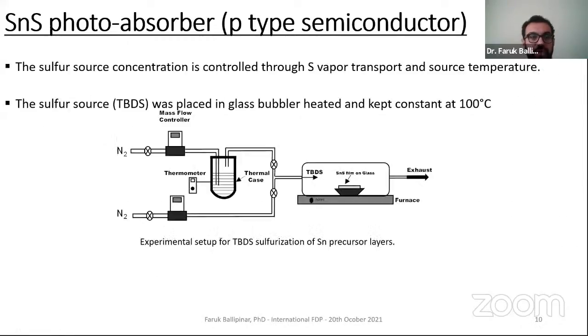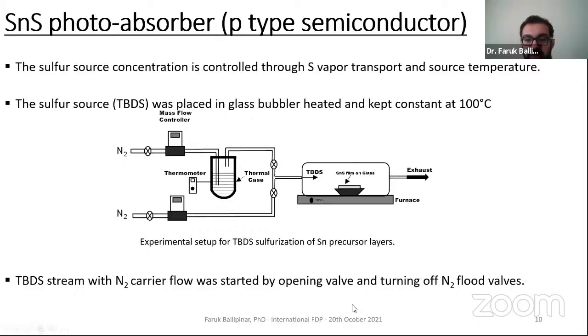Okay, so this is the experimental setup. We put the substrate in the middle of the furnace, and the TBDS source was placed in this glass bubbler and heated, kept at 100° below the boiling point of this liquid. Once the furnace reached the desired temperature, by opening the valve, the sulfur comes through this valve and the sulfurization starts.